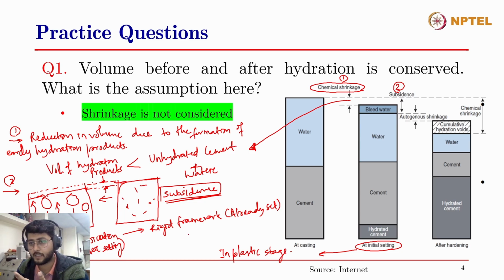The autogenous shrinkage that occurs after the setting is very little in amount, and therefore, as you can see in this view graph, the total chemical shrinkage is much higher than the autogenous shrinkage, right? Because the chemical shrinkage is the shrinkage when the concrete is still in the plastic state, it is able to flow, so if there is a volume change, it can undergo that. But after it has set, the autogenous shrinkage is due to the chemical reaction still going on, and therefore it can't undergo as much volumetric reduction as it would in a plastic state. So the autogenous shrinkage is less in amount. All right. So these are the different types of shrinkage that it undergoes within a few hours to 1 or 2 days of the setting, right?